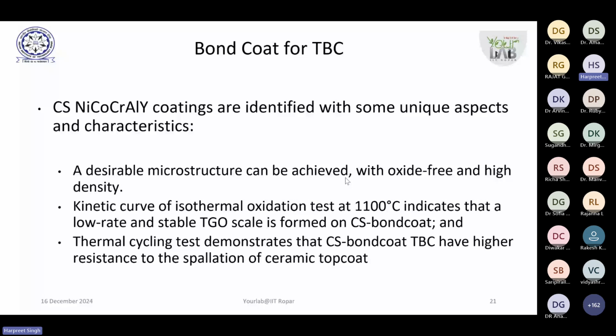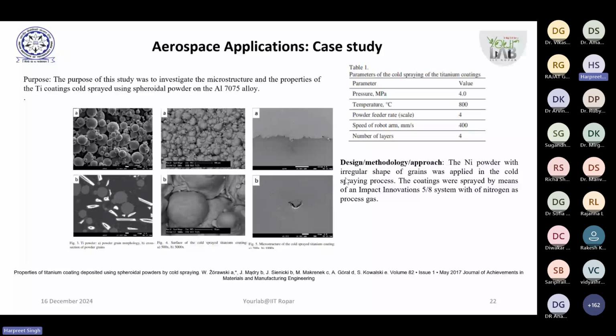So there we typically use thermal barrier coatings, and the architecture of these coatings is that usually we have the superalloy blade on which we apply some bond coat, which is typically metallic, and then we apply the ceramic coat, right? Now, a lot of research is being done on how to achieve good properties in bond coats as well as these top coats, right? There's a problem of life, there's a problem of hot corrosion and all that, right? A lot of research is being done, and cold spray has also been tried in these kinds of applications, right?